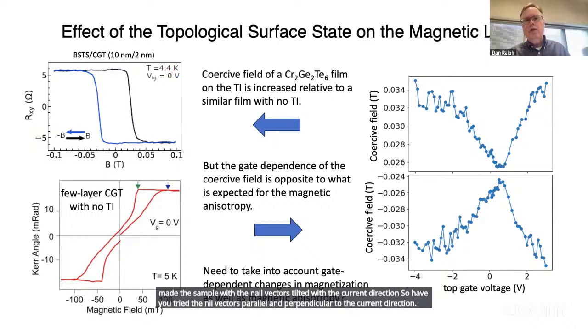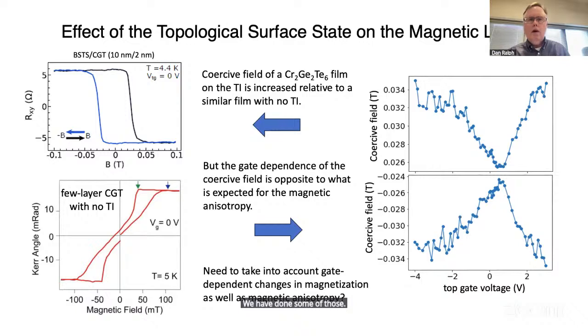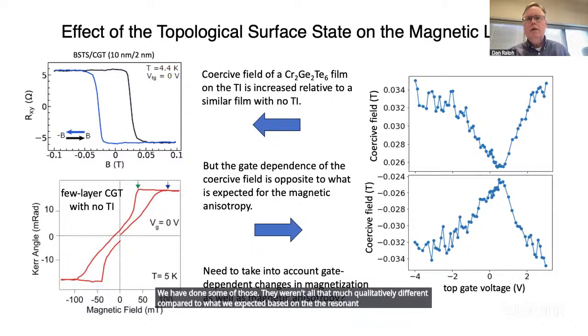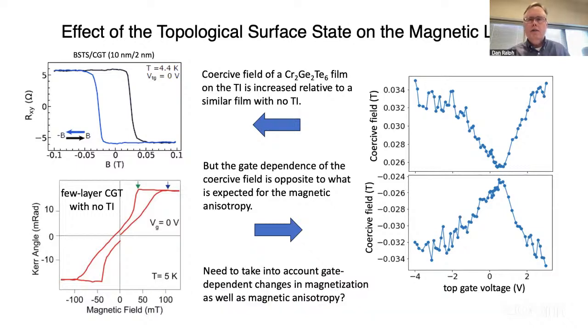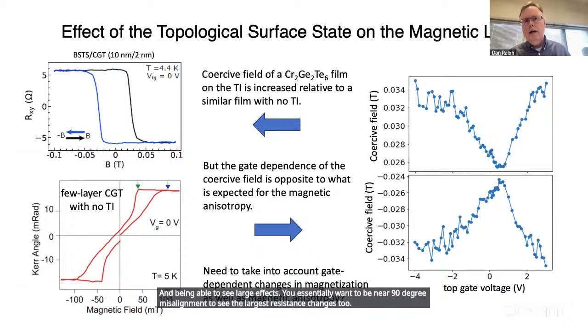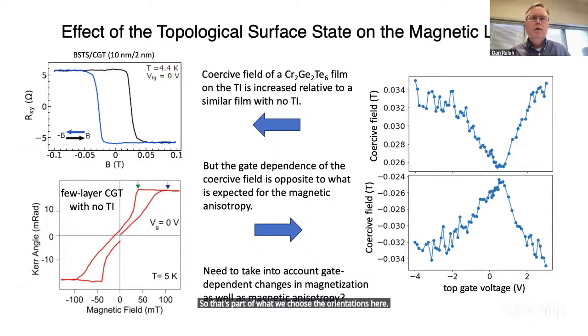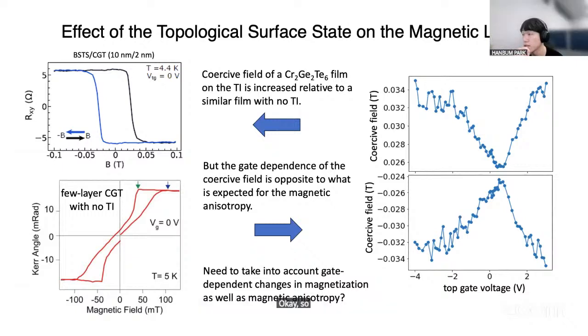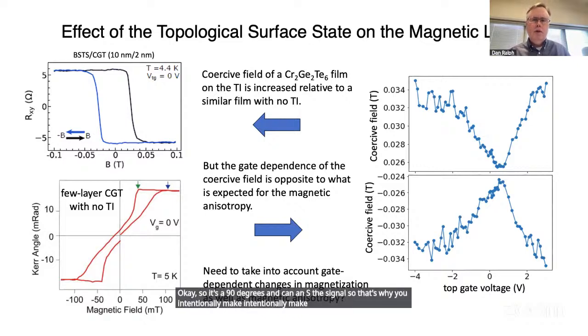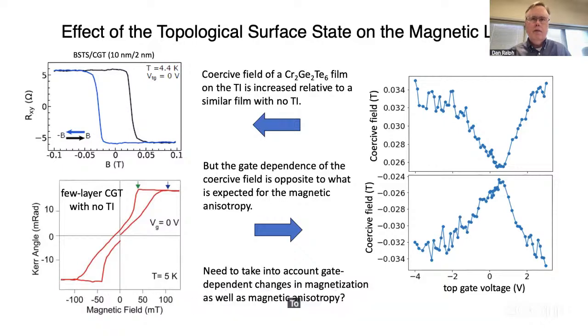We have done some of those too. They weren't all that much qualitatively different compared to what we expected based on the resonant absorption measurements. But having things tilted just gives us a bit more control over the relative orientation and being able to see large effects. You essentially want to be near 90-degree misalignment to see the largest resistance changes too. So that's part of why we chose the orientations here. Okay, so the 90 degrees can enhance the signal, so that's why you intentionally make it that way. Yeah, so we almost always have a magnetic field bias to give us a close to 90-degree offset to be able to see large signals.